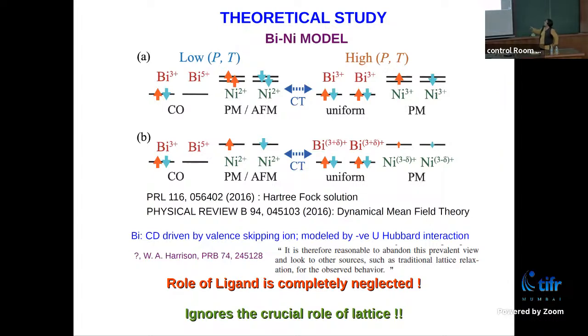So there are two calculations. It's a very similar calculation. There was one which did some Hartree-Fock kind of method, and a subsequent one where they did the DMFT, the dynamical mean field theory. And for the bismuth, their model was based on only bismuth and nickel, no oxygen, nothing.